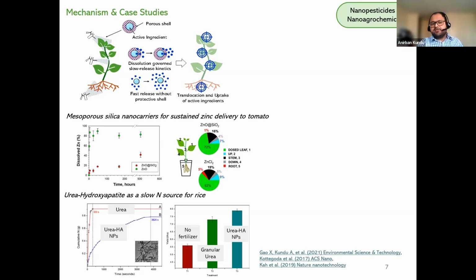And on the right, we actually tracked this zinc across the plant. So we dosed these materials in the leaf, which is why you see a lot of green area shaded, which is the concentration of zinc in the leaf. But then in 3 days, the zinc reached other parts of the plant, which are the other areas of the pie chart. So it reached the stem, the root, and other areas in the plant, which basically told us that zinc in silica nanocarriers were an effective delivery agent of zinc to tomato plants.